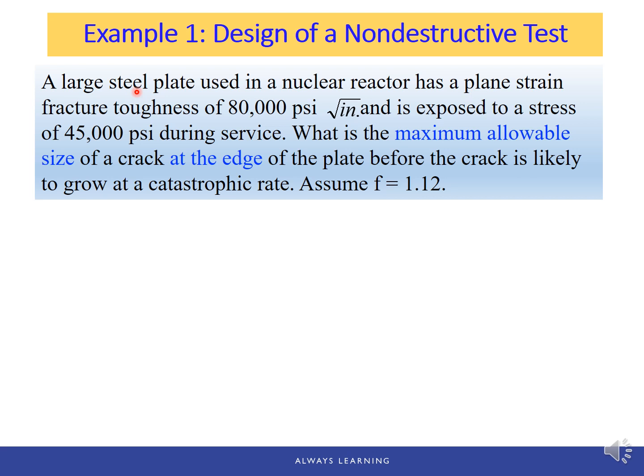Example 1. A large steel plate used in a nuclear reactor has a plane strain fracture toughness of 80,000 psi square root inch, and it's exposed to a stress of 45,000 psi during service. What is the maximum allowable size of crack at the edge, which means at the surface of the plate, before the crack is likely to grow at a catastrophic rate? Assume the geometry factor F equals 1.12. Again, sometimes in some resources you will see this letter F. In some books, for example in the textbook, it uses the letter Y for the geometry factor. But we know they are the same.